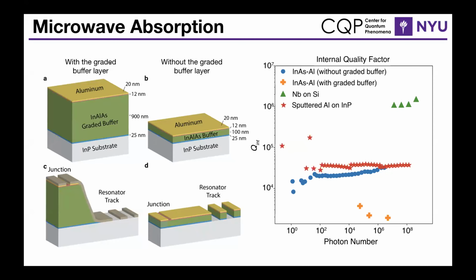So doing it on this structure with the graded buffer layer, we expected this to perform not that well due to the loss you get in the bulk because of defects in the graded buffer layer. And what we saw was that on these types of materials, you're only able to get quality factors up to a couple thousand. And so this definitely is not that good when you want to make qubit devices out of this material.